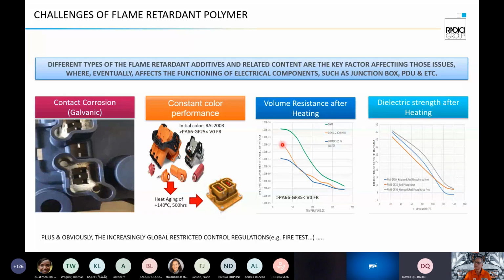But you can see here, after aging at different temperatures, the volume resistance drops very quickly, and this would be very dangerous, let's say, if the part suffers very high voltage, then this part will be penetrated by the high voltage.